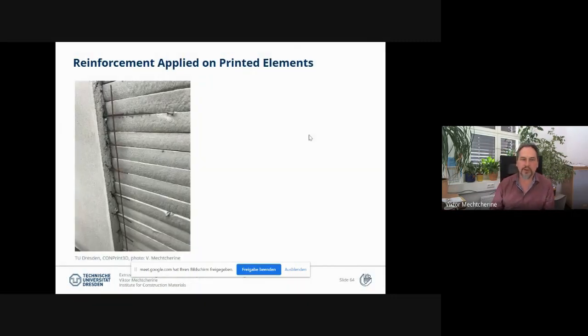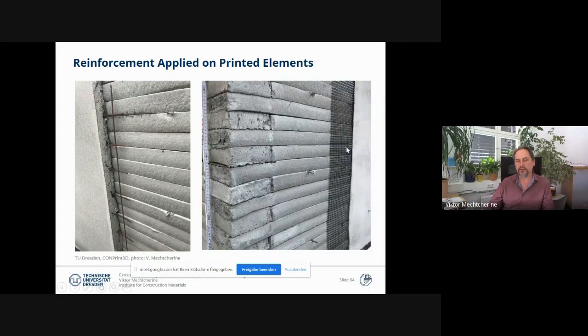Another straightforward approach is to print first the wall and then apply the reinforcement on the printed wall, as shown here in the case of our project. You see there are some mounting elements here, and then you just place the mesh, steel mesh, steel mats here on this mounting, and then apply by spraying or by other technique the cover layer. So, of course, you can use also textile reinforcement for change.